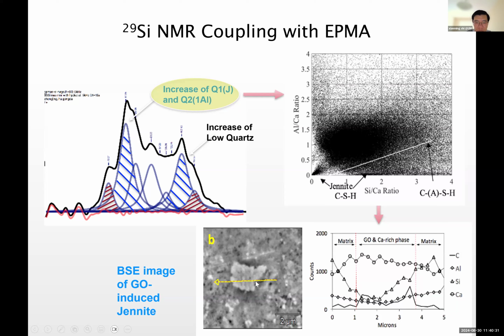And then you do the 1D line scan on the surface, and you can see the richness of the carbon. Compared with the adjacent area, the carbon is a little higher. That means you got some graphene oxide here, most likely. And then you see some other elements. So all the different data points eventually converge and tell the same story. Now you got more graphene oxide induced jennite phase.